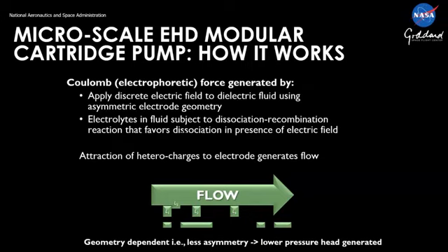All these dimensions are important. L1 and L2 give you the asymmetry, so you can develop the flow. L3 is, of course, the distance between the positive and negative electrodes. And then L4 is a characteristic length to keep one stage from affecting the other. Now, when you apply the electric field to a dielectric fluid, the impurities in the fluid actually are ionic, and they break down into positive and negative ions, and they are attracted to the oppositely charged electrode, and that's how you generate the flow. So it's very geometric based. The less asymmetry, the lower pressure head, and in the case of these EHD pumps at microscale, it's probably the most difficult case. So that's why we went to the manifold pump system. Next one, Sean.